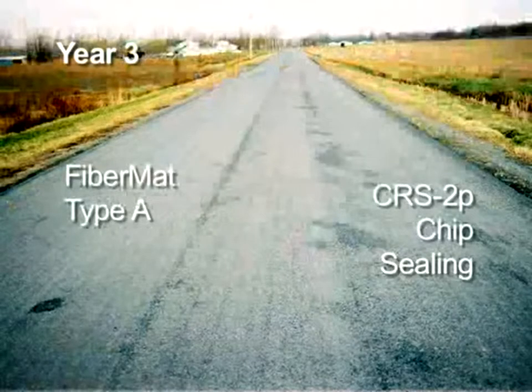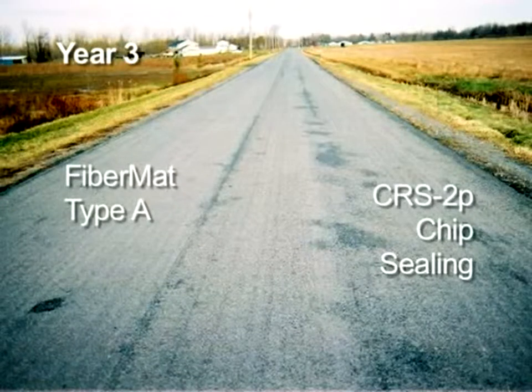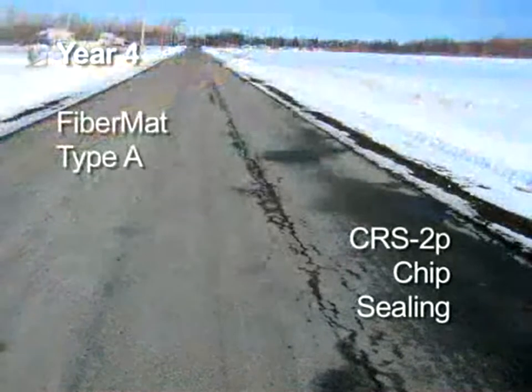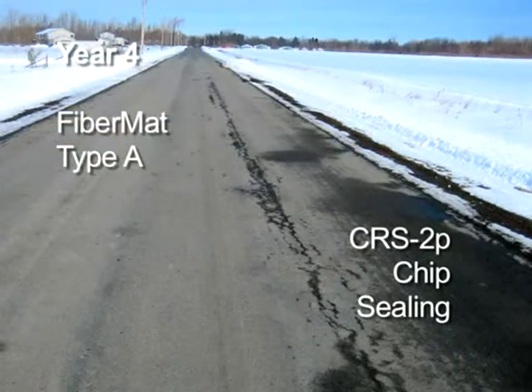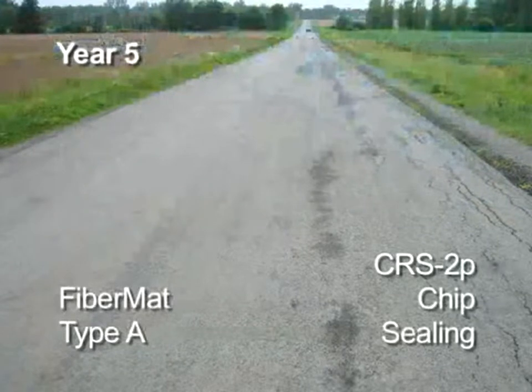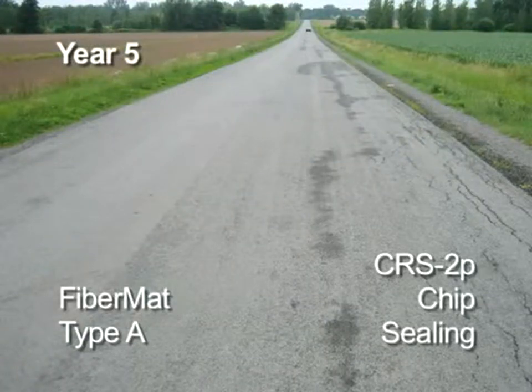In January 2006, further evidence of snowplow damage was noted, along with water pumping from the lower layers on the chip seal side, while only nominal slight damages started to occur on the FiberMat side, all the while the membrane itself was still intact. In January 2007, the chip seal side showed significant deterioration, becoming now a candidate for total rehabilitation, while the FiberMat side, after over 4 years, only just started to show minor damage. By summer 2008, the original chip seal side fully deteriorated, with aggregate being lost and the surface raveling along with